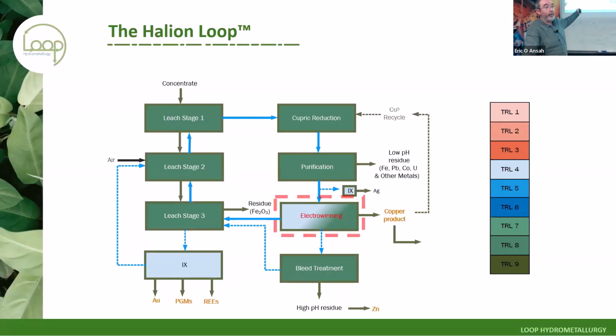So effectively what happens is the freshest mineral reacts with cupric and pushes, by Le Chatelier's principle, the copper into about 97.5%, 98% copper 1. We then run it with a little bit of copper recycle to 100% cuprous. Now, the advantage is that cuprous is pH stable, whereas a lot of other metals are not. So then all you need to do is raise the pH a little bit, and most of your contaminant metals simply drop out. That's an opportunity to also capture other metals, lead, cobalt, uranium, other things as byproducts, if that's desirable for your project.